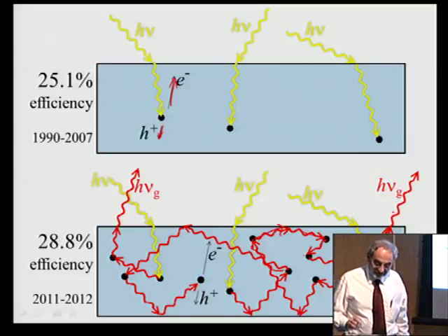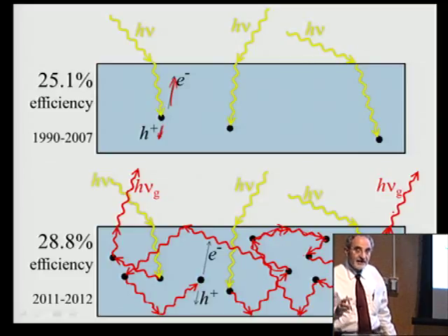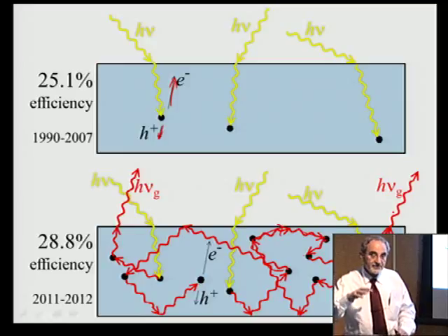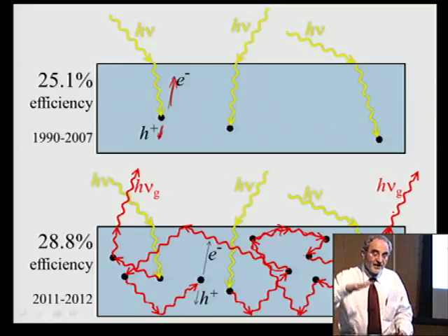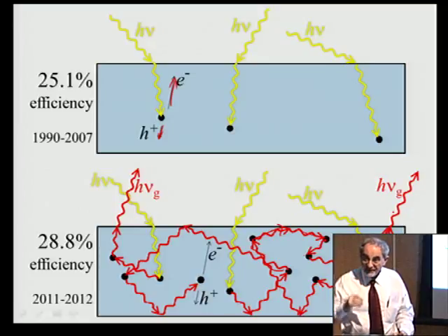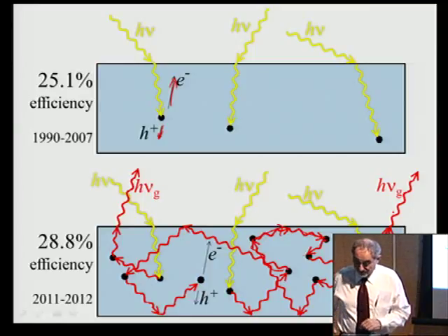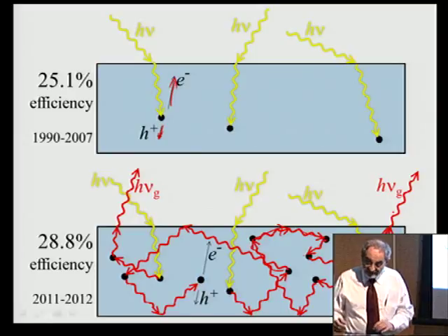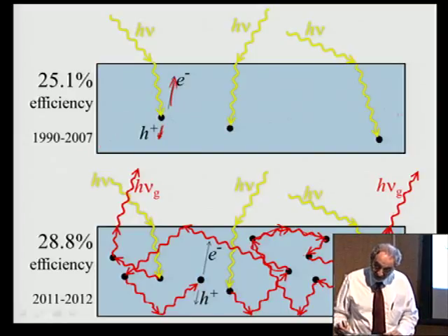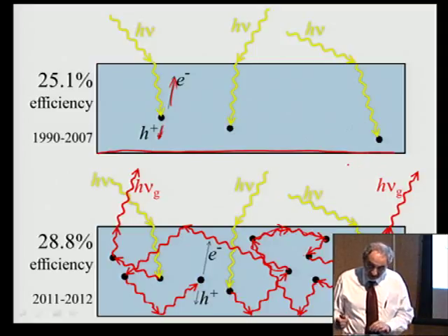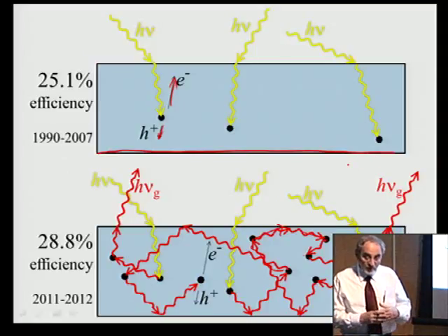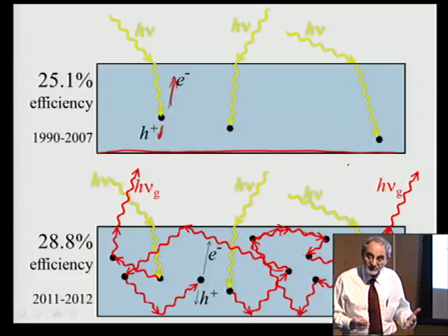That in one sun, in this new concept of solar cells, there could easily be 30 to 40 suns of infrared luminescence bouncing around inside a one sun solar cell. And that is a prerequisite for achieving the theoretical efficiency limits. And so it's this recognition, going from this simple picture of a solar cell, which is in all the textbooks, to this more nuanced description of a solar cell, where the solar cell has to manage the external luminescence.